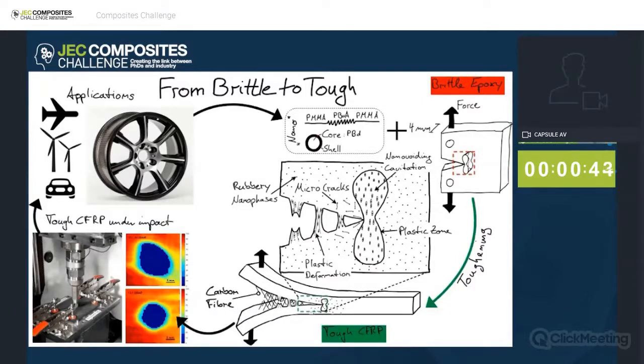So in the end, and that is one of the most exciting results, we were able to drastically reduce the damage volume. As you can see on the lower left side of my slide, this is just a 2D representation, but we were able to reduce the damage volume by about 67% in a thin laminate. If we think about future applications, we will probably be able to drive through the Swiss Alps without any damage in our rim. So thermodynamically driven self-assembling is, I think, what we need in future toughening applications for epoxy systems.